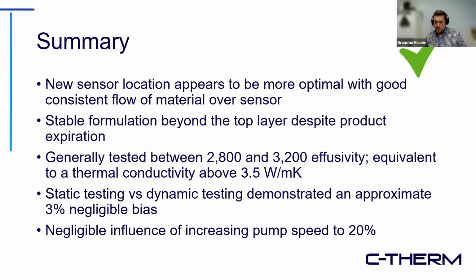During the good or stable middle section, the material generally tested between 2,800 to 3,200 effusivity units, which is roughly equivalent to a thermal conductivity of above 3.5 watts per meter Kelvin, which is better than the 3 watt per meter Kelvin specification. Next slide, please.